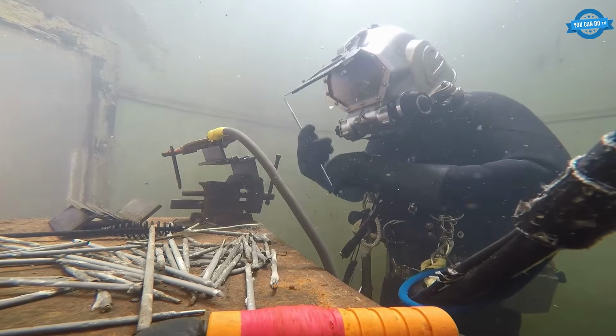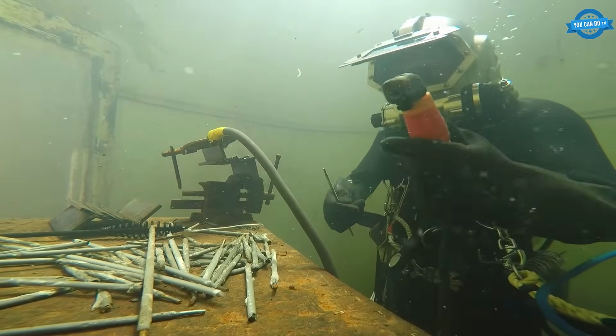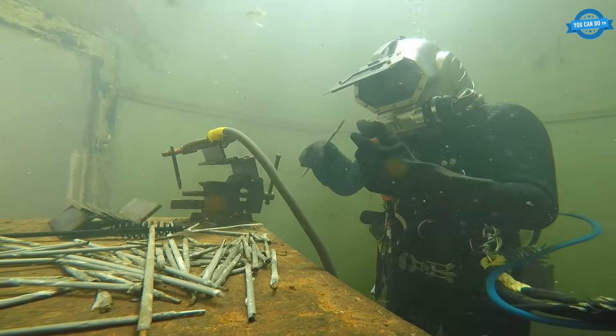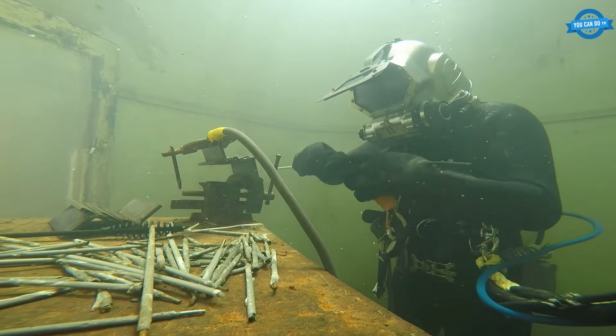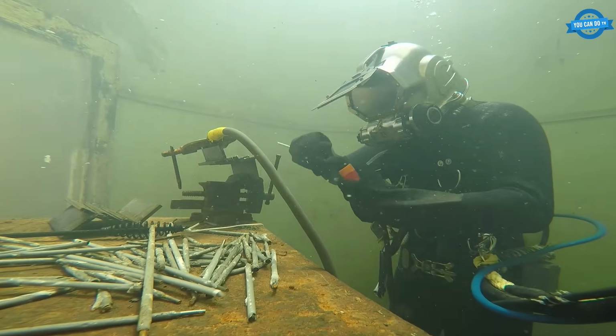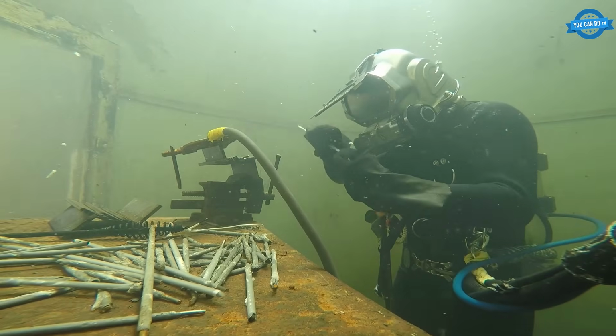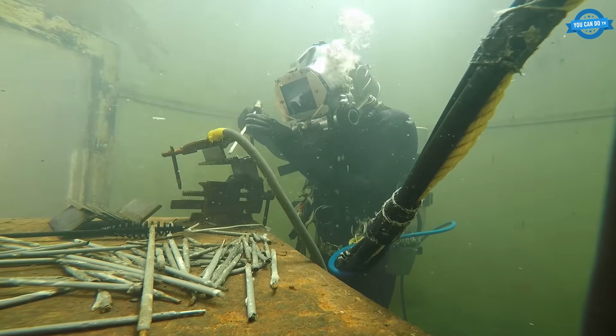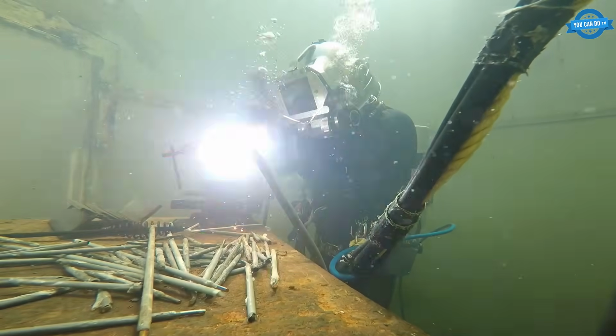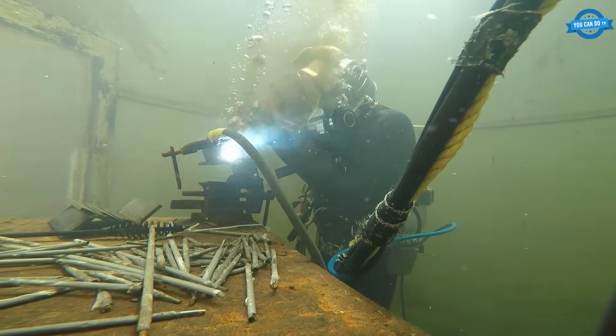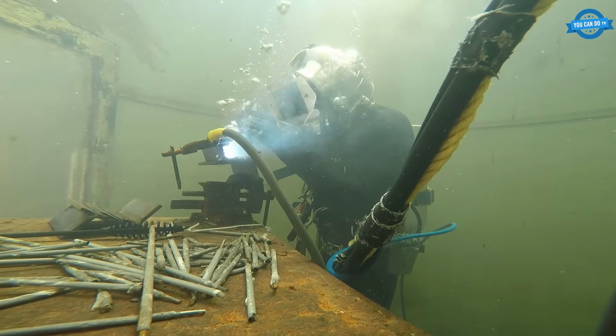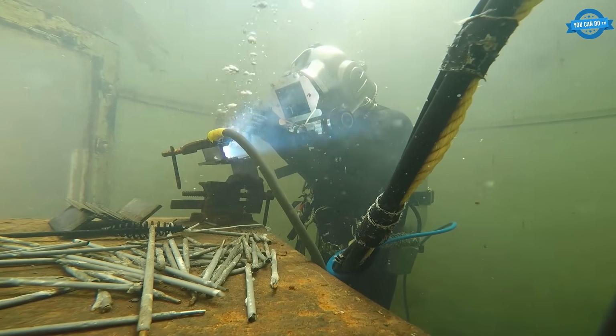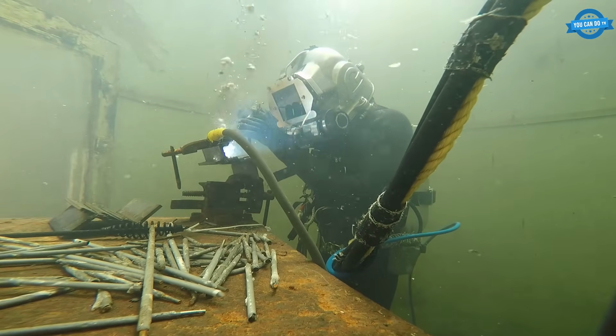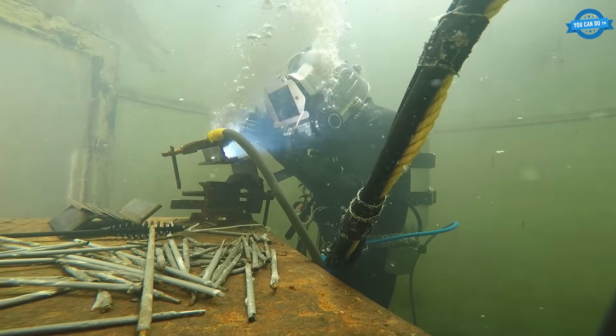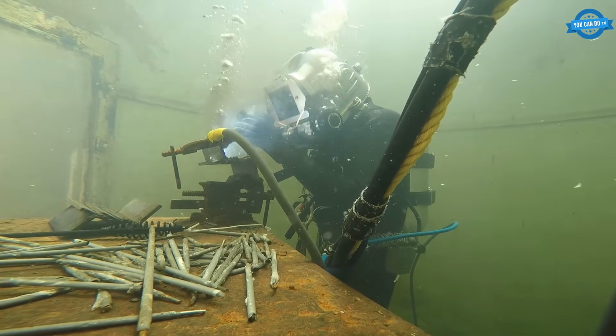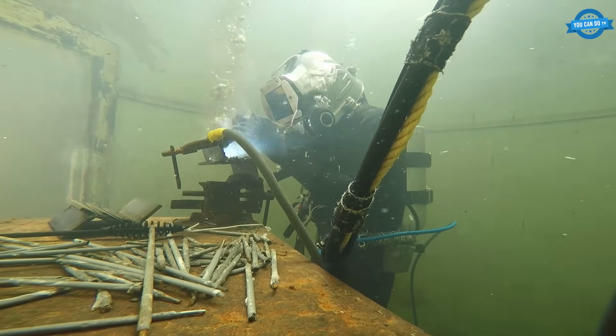Even the best surface means little if a hidden crack is sitting just inside it. The real question is whether the structure beneath the weld is as solid as the surface makes it appear. A diver tests the welding tool first, then fixes the workpiece to a secure footing on the seabed. With positioning confirmed, an electrical arc strikes between the electrode and the steel. The metal melts and fuses cleanly despite being fully submerged.